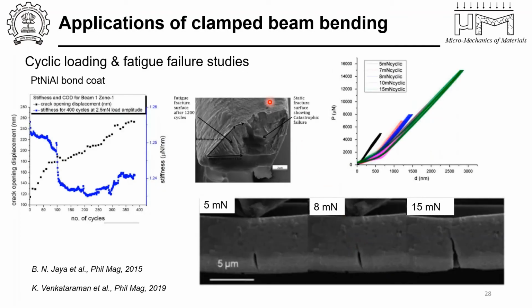Similarly, when you have cyclic loading or fatigue applications, then the slow crack growth can be easily captured using clamped beam bending. There is a good amount of work published by Professor Vikram Jayaram's group, which shows the change in stiffness and correlates it to the increase in crack length corresponding to different numbers of cycles, and one can sort of predict the fatigue failure in structures, including in thin films and coatings as well.